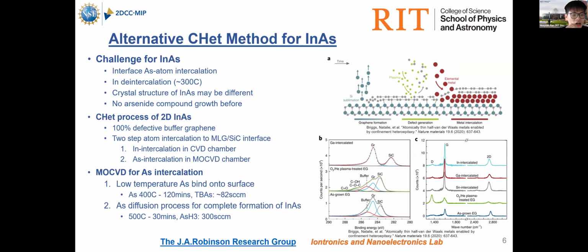However, to thoroughly use CHet for indium arsenide growth, it still has a few challenges. First of all is the interface arsenic atom intercalation. Arsenic atoms are hard to stick to the silicon carbide substrate. Therefore, we need something for them to bind to. And that's why we are breaking the growth process into two steps. We're going to grow and intercalate indium first, and then arsenic.